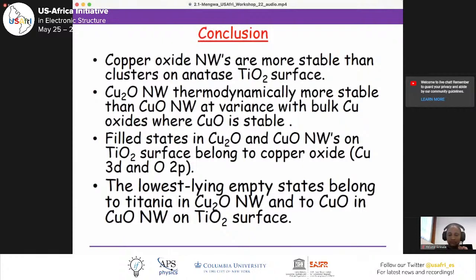Now, the conclusion is that the copper oxide nanowires are more stable than clusters on the anatase TiO2 surface. Cu2O nanowires are thermodynamically more stable than CuO nanowires. These are at variance with what we see in the bulk, whereby the copper oxide that's most stable is CuO.